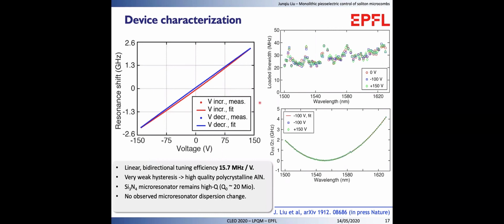We first characterize the sample. On the left, it shows the resonance tuning versus the voltage applied. The linear tuning efficiency is 15.7 MHz per volt. A very weak hysteresis is observed, showing that our aluminum nitride is high quality polycrystalline. On the right shows the microresonator Q and the dispersion with different applied voltages. As seen, there's no Q degradation and no dispersion change.